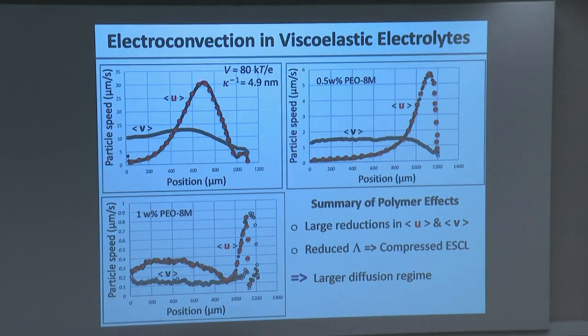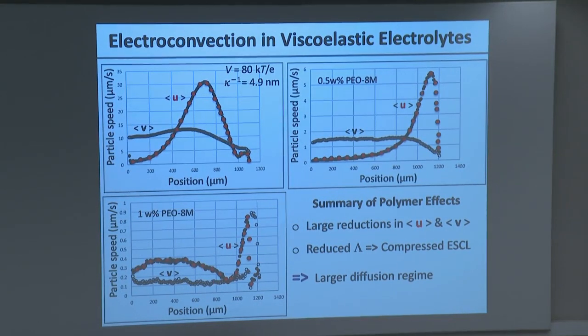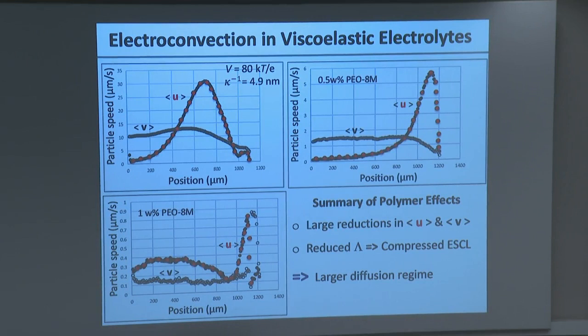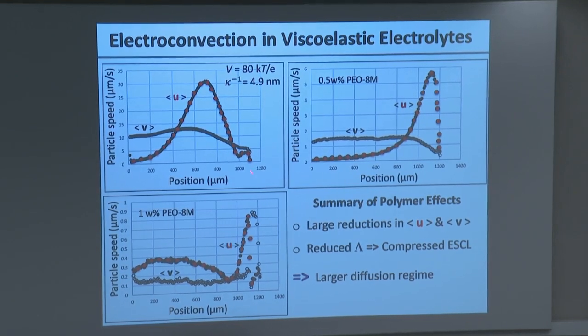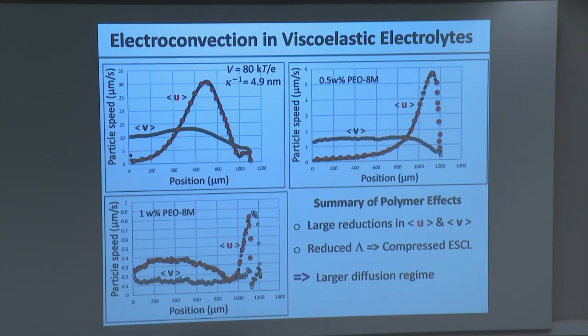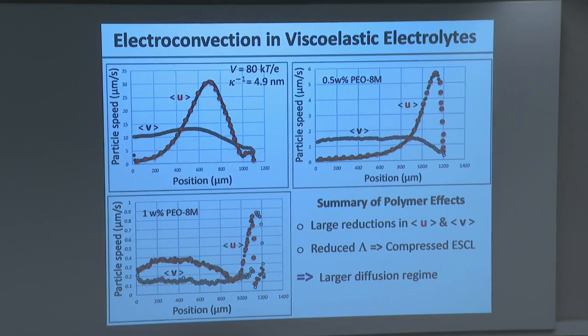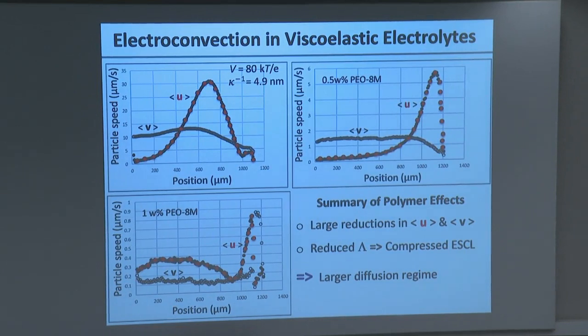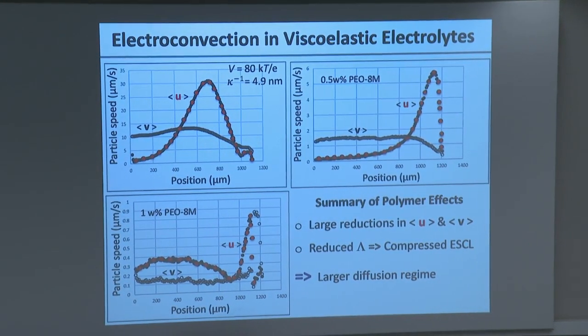So for example, if we look at the peak value in U, we see that it goes down by something of order a factor of 4 to 5, okay, in the presence of 0.5 weight percent polymer. And when I go from 0.5 weight percent to 1 weight percent, it goes down by another factor of 5 to 8, all right, indicating that I'm suppressing this flow like crazy in the presence of this polymer. What we also notice is that the distance at which the peak appears, right, so this is where the so-called boundary layer that I mentioned before appears, begins to shrink. So as we add polymer to the system, the boundary layer begins to shrink, meaning that any flow is being confined to progressively tighter and tighter layer near the interface where it's less harmful. All right, so the visualization experiments tell us, oh, the polymer is appearing to suppress the electroconvective flow.